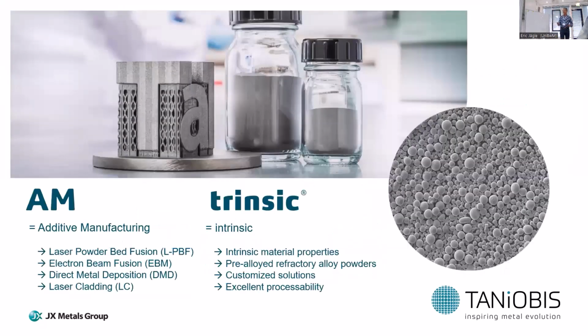One of our product lines is quite new, the so-called AM intrinsic powders. Those are specially developed powders for application in additive manufacturing processes. AM, of course, stands here for additive manufacturing, covering all relevant processes: laser powder bed fusion, electron beam fusion, direct metal deposition, laser cladding, and intrinsic, indicating that we are introducing the desired or required properties of the final build already in the precursor materials, so in the alloy powders. This is done by producing pre-alloyed refractory metal powders, usually according to customer requirements.